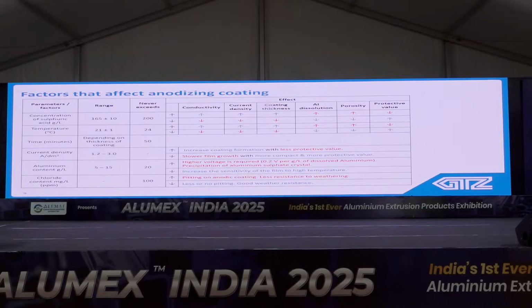Aluminum content in the electrolyte is also important. If the aluminum content is more than the maximum range, then higher voltage will be required, which is not desirable. Then heat generation will be more, and the coating roughness or aesthetic look will be poorer. Then chloride. Chloride is detrimental for any corrosion resistant coating. The same logic is applicable to anodizing coating also. The maximum tolerance is 100 mg per liter, or 100 ppm. So for anodizing, DM water, chloride-free water, is desirable.